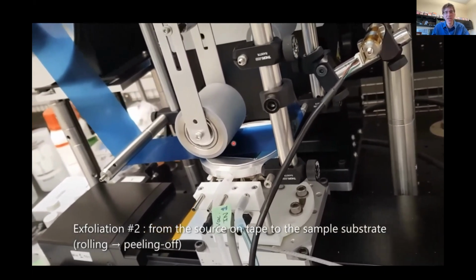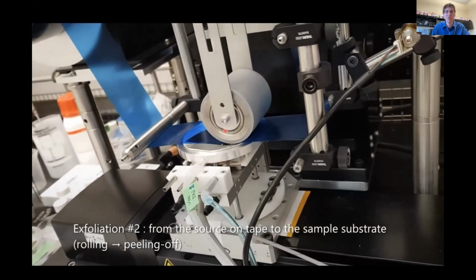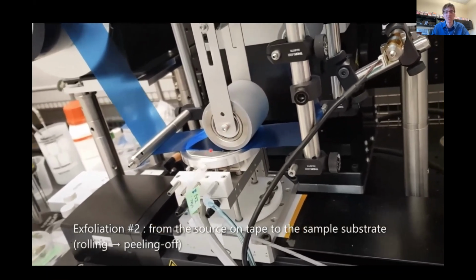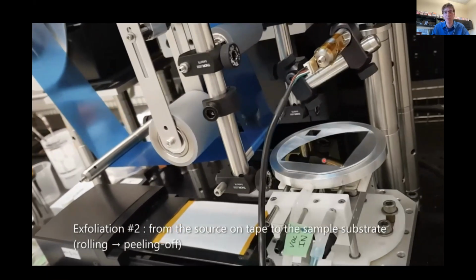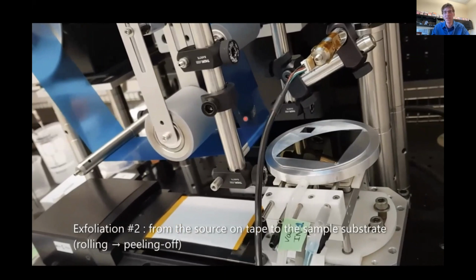And there's some flakes here. You can't quite see them from this angle. But when we do this rolling operation, hopefully some flakes are now stuck onto the substrate and we peel off. These were the flakes that we transferred, and you can't see it very easily, but there's a bunch of flakes now on the substrate, okay?